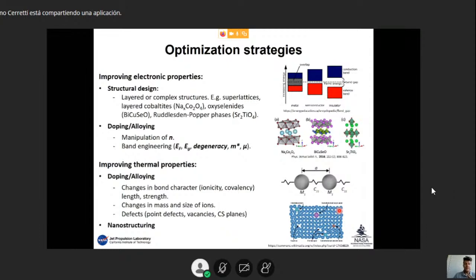Therefore, for the improvement of the electronic properties, we can go for the structural design. So we can try to design a complex crystal structure that has maybe different layers, where each layer is responsible for a different thing. For example, in this case, for the sodium cobalt oxide, we have these layers that are really nicely formed, where the electrical conductivity is really high, therefore they boost the electrical conductivity. But then in between we have big atoms that are connected to the other layers with weak bonds called van der Waals bonding. And these weak bonds and the fact that we have these layers is what generates active phonon scattering centers, and therefore reduces the thermal conductivity.